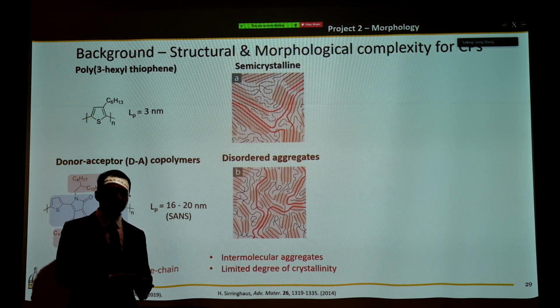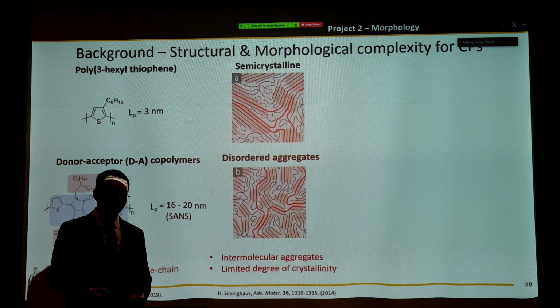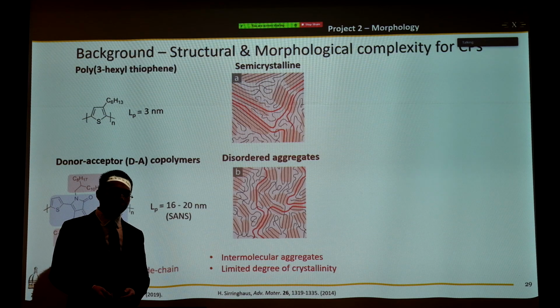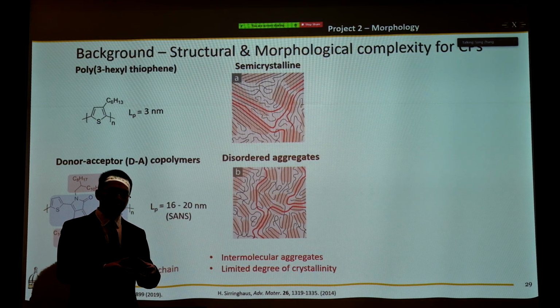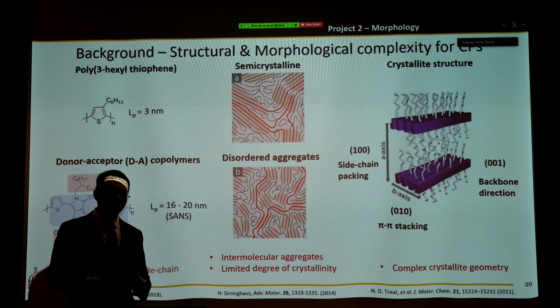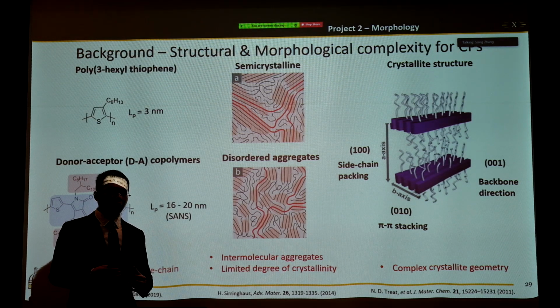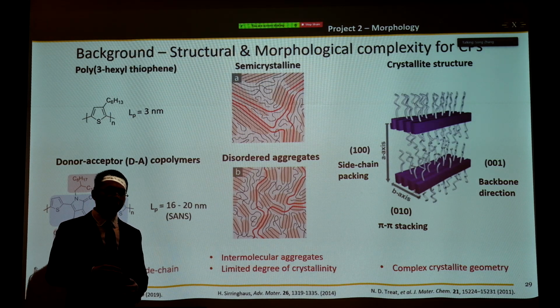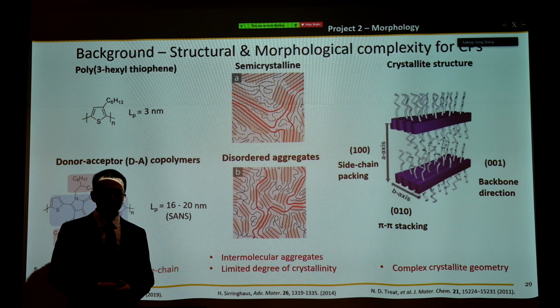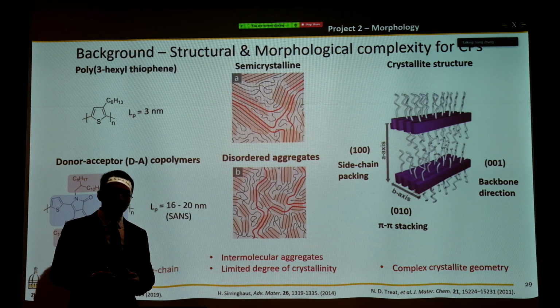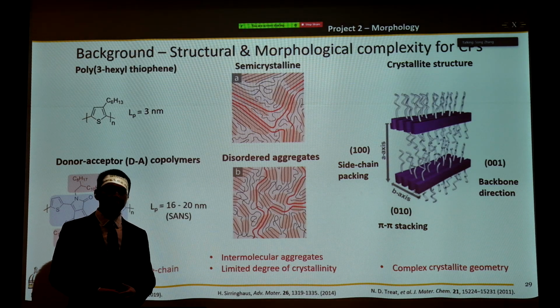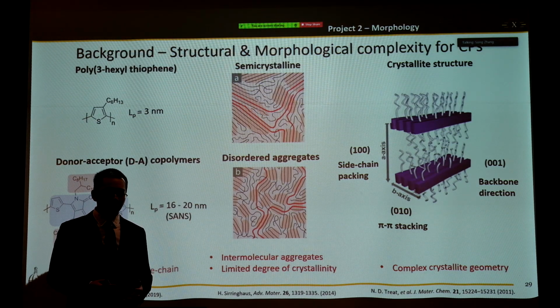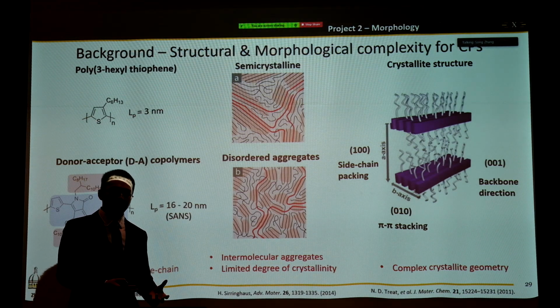And that's why they can form this semi-crystalline morphology. However, for these super rigid donor-acceptor polymers, it turns out chain folding is not that efficient, and in the local crystallite, it's very different. For example, what's shown here is different clusters of polymer chains are interacting with each other, as shown in the red regions. And in the crystalline structure, the packing phenomenon is very complicated as well. So we have 3 directions of interest. The first direction is along the polymer backbone, which we call 001, and that is composed of alternating donor and acceptors. The second direction is the B-axis here. It's called pi-pi stacking and represented by this 010 peak. The third direction, or the A-axis, you can see it is side chain packing, or we call it lamella packing. And this is very different from traditional polyethylene as well.